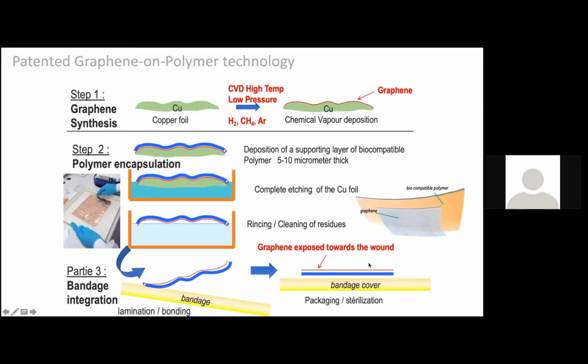So how can we make this for wound healing? Instead of coating silicon or a hard sample, we decided to make a transfer on polymer. So we start from monolayer graphene on copper, like it has been shown yesterday. We deposit a supporting layer of a biocompatible polymer, typically 5 to 10 microns thick. And then we etch back the copper foil and we remove all copper ions. That's very important. And you end up by putting upside down the layer with the graphene exposed and backed with biocompatible polymers. And this we insert in a typical bandage.